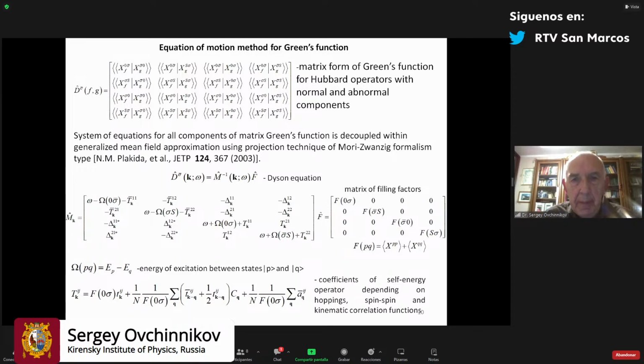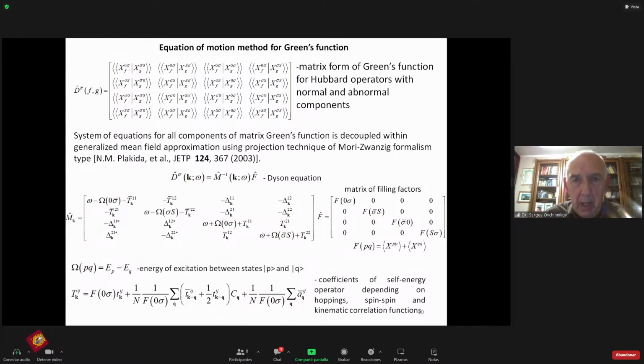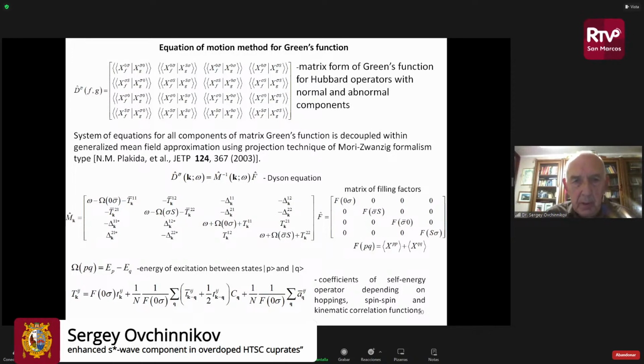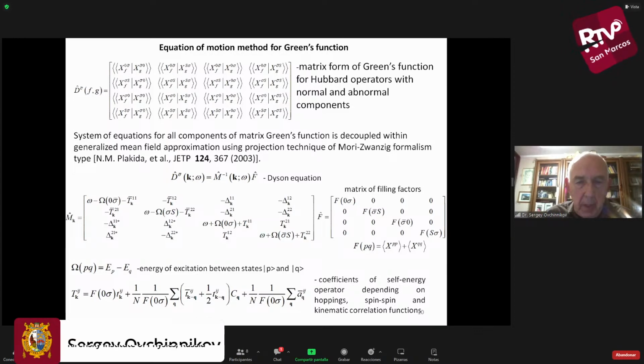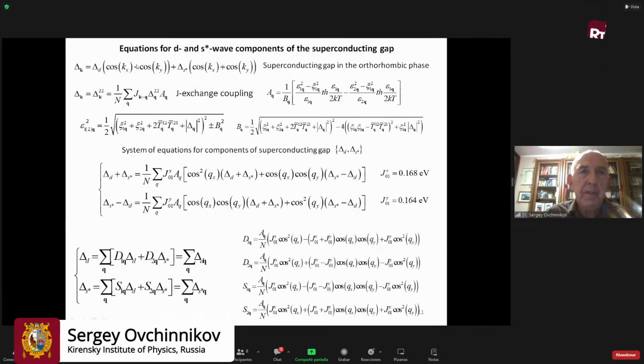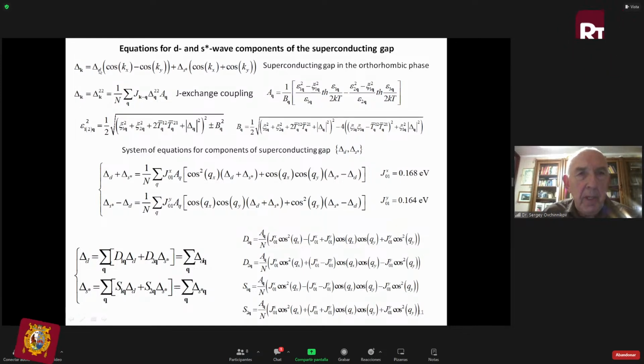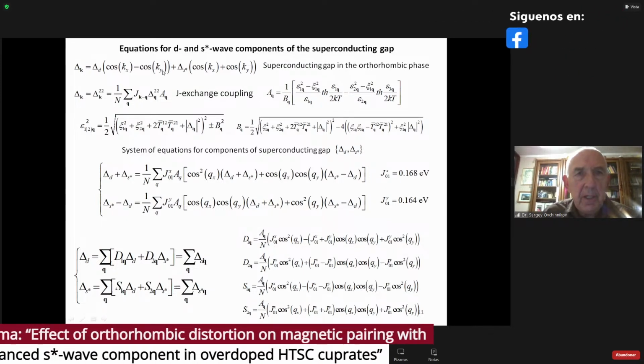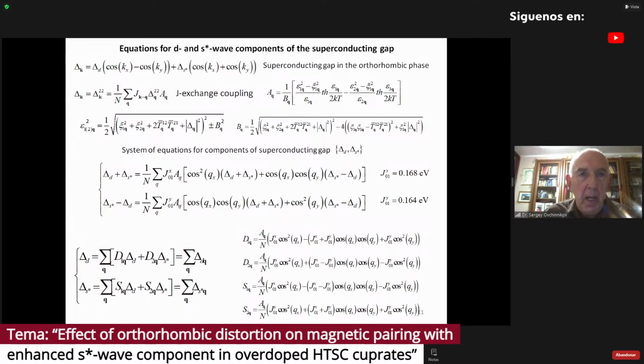So, well, we did not develop any new method. We just used his method, only for the large size of the matrices, because it is not the Hubbard model. It is the pd model with oxygen and copper. So all these matrices are given here. And then a system of equations for the d and extended s wave components of the superconducting gap. So the total gap, delta of k, is given by a combination of the d wave gap, delta d, and the extended s wave gap. And for this gap, we have a Gorkov type equation. And this is the superconducting energy epsilon.